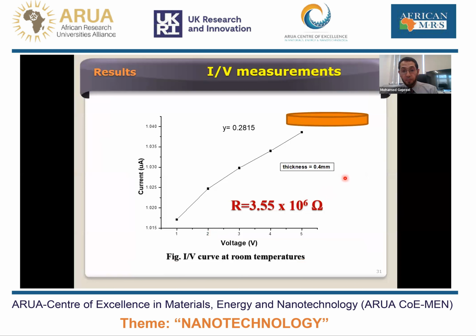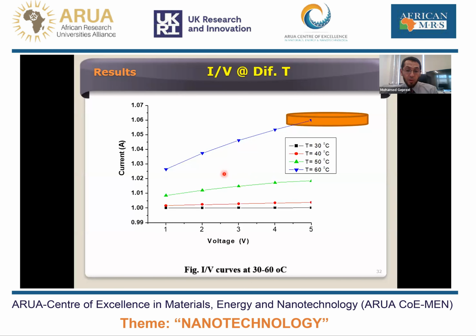We see here that the current is increasing with volt. So it is one of the measures of the semiconductor nature of the material. If we think also about the effect of temperature, the electrical conductivity, or electrical resistivity, is also changing. The conductivity is increasing with increasing temperature, which means another sign of the special physical nature of this lead oxide nanopowder mixture. As we can see here, as a function of temperature, this is high temperature, 60 degrees, and this is room temperature, increasing in this way.